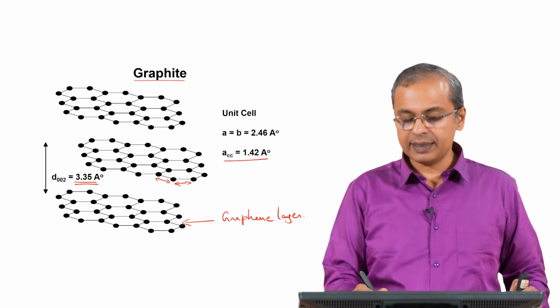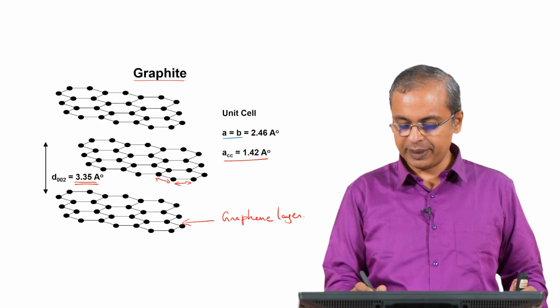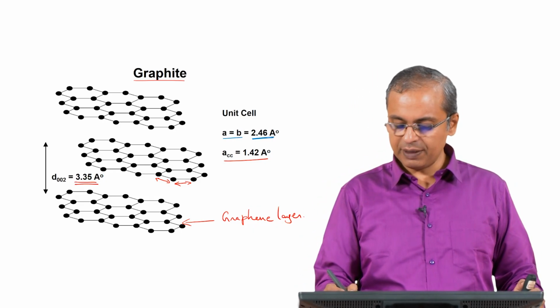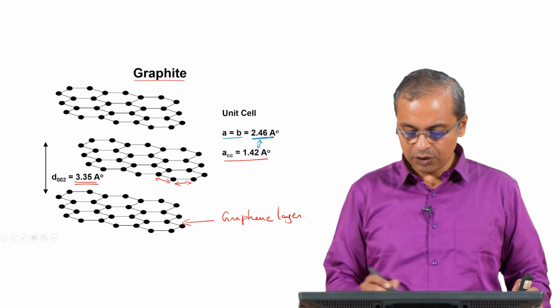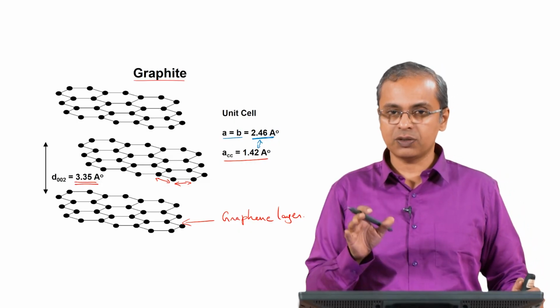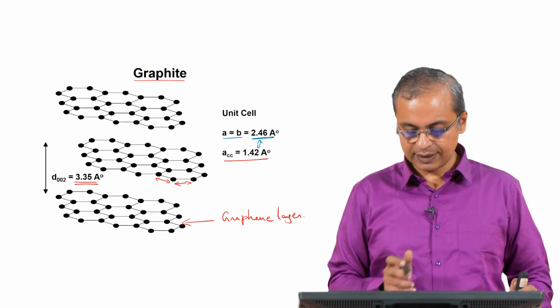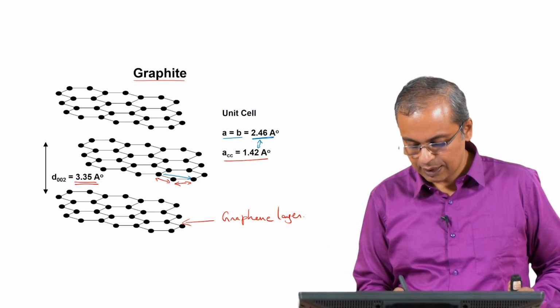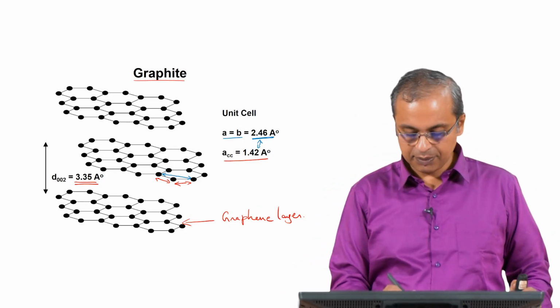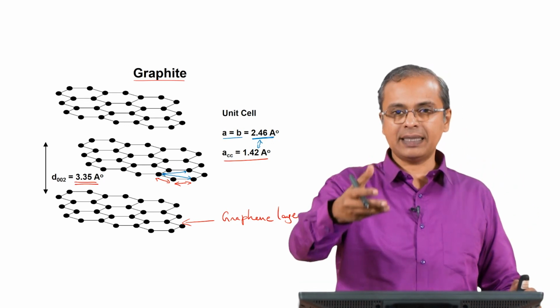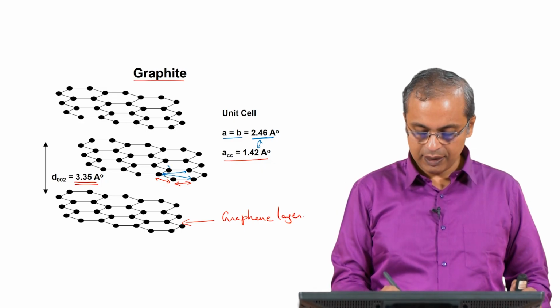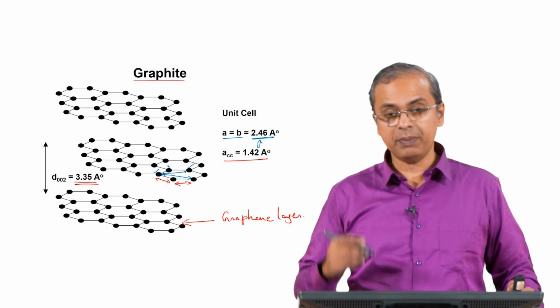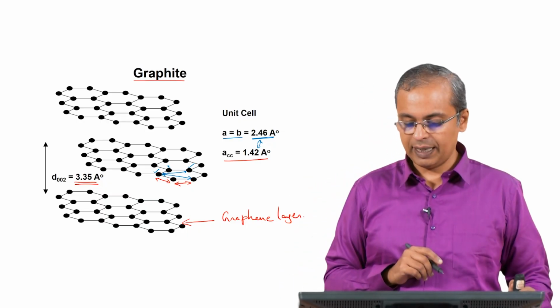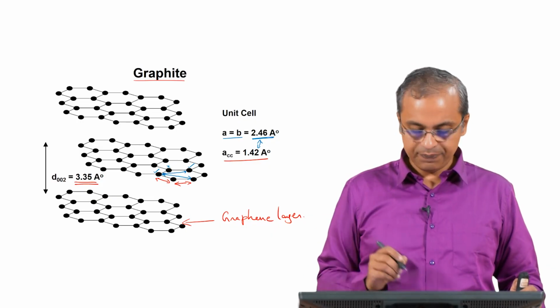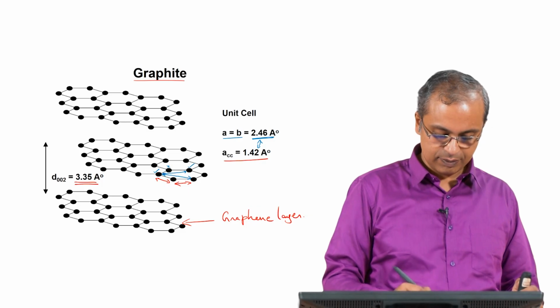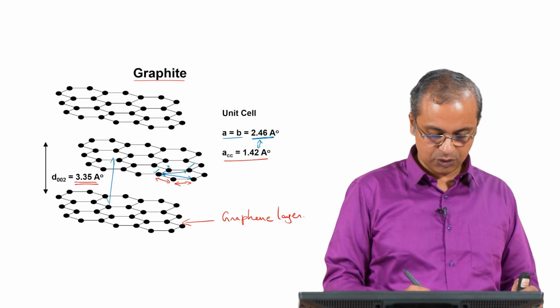Versus when you look at the crystallographic unit cell parameters, you have A equals B equals 2.46 angstroms, which is different from this 1.42 angstroms. That is because the convention with respect to graphite is not to call the carbon-carbon bond length the A axis or B axis, but rather to call this distance your A direction, and similarly this distance would be your B direction. So, it is not the immediate next neighbor, but the neighbor after that. If this is your origin, then it is not the first neighbor, but the second neighbor that you are accessing, and that distance is the A or B unit cell vector. The D002 spacing is the spacing between these planes, right. So, from here to that side, that spacing is your D002 spacing.